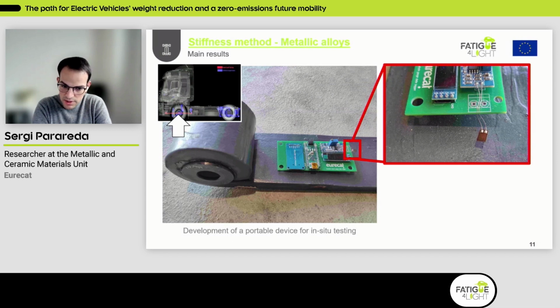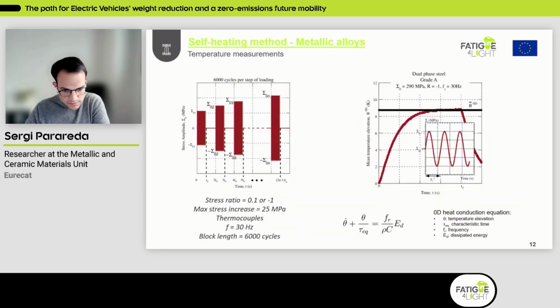And the main point is that we are working on developing these new devices to monitor the strains and get the data directly at component level. On the other hand, we have this self-heating method, and the idea is very similar to the stiffness method. But here what we are doing is monitoring the temperature evolution during the test.